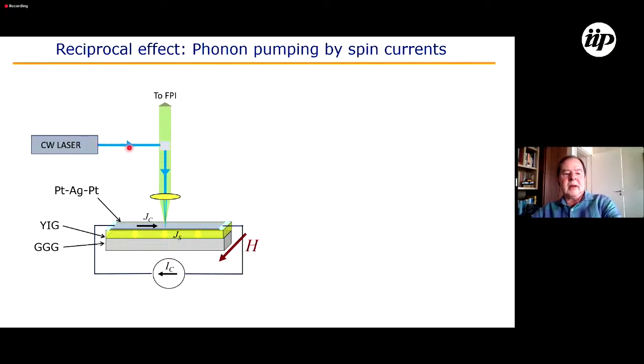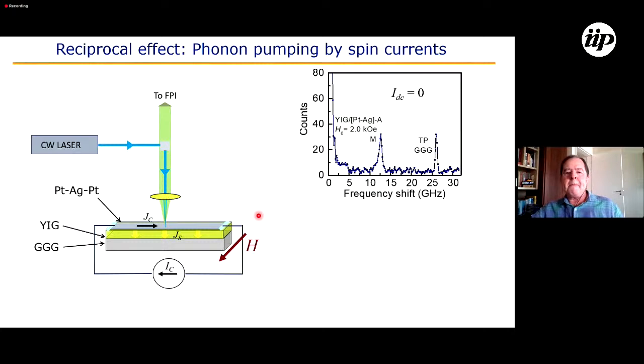So a laser is shining on the film, and we see the reflection go to the Fabry-Perot interferometer. So this is the result of the Brillouin scattering. This is the laser pulse. This is with no current. This is the magnon pulse. This is the phonon pulse. Phonon of the substrate, GGG.